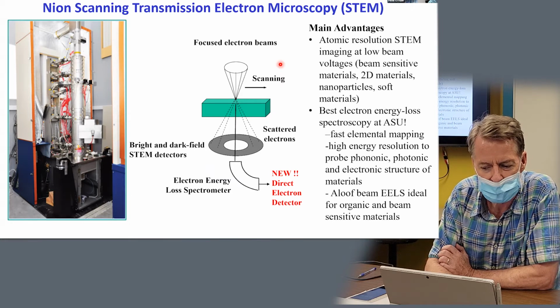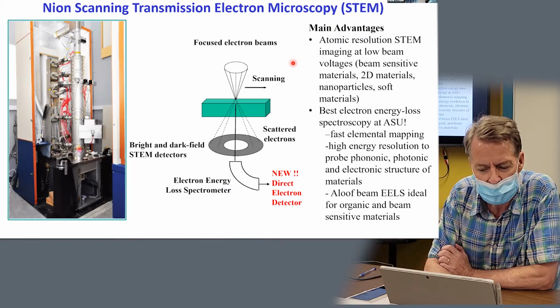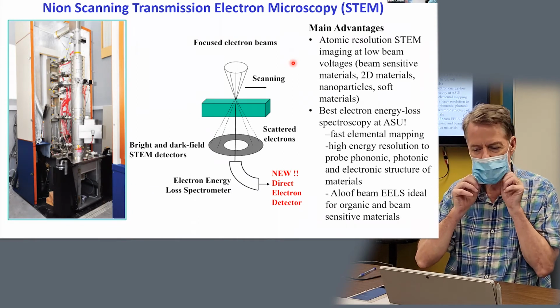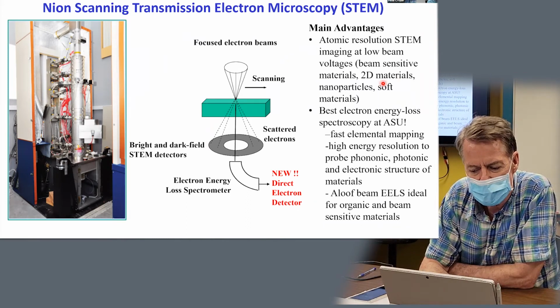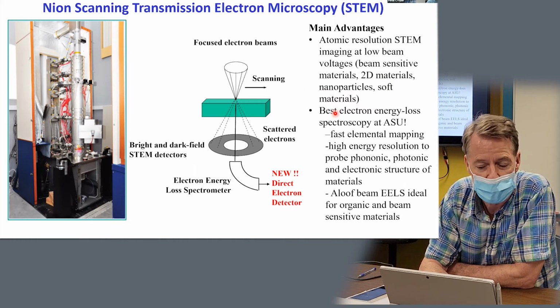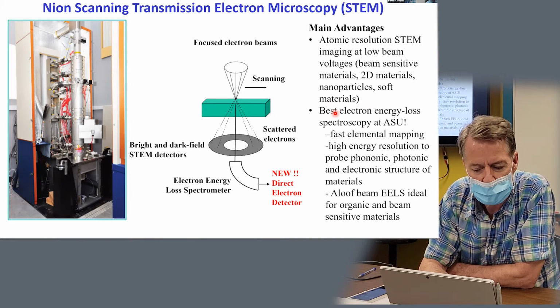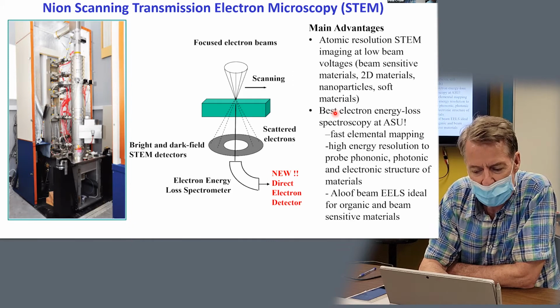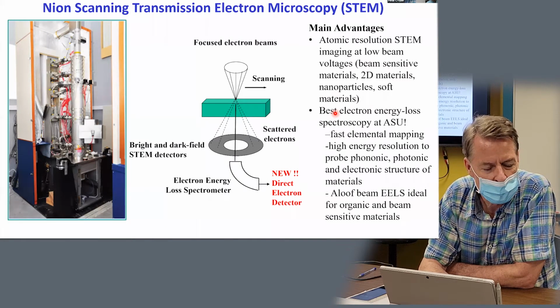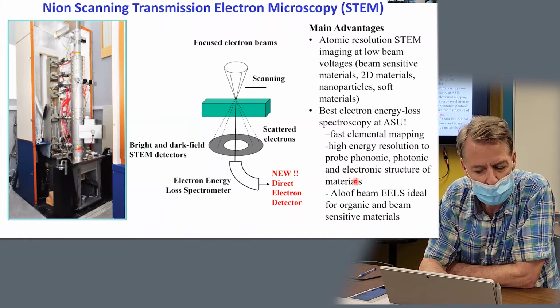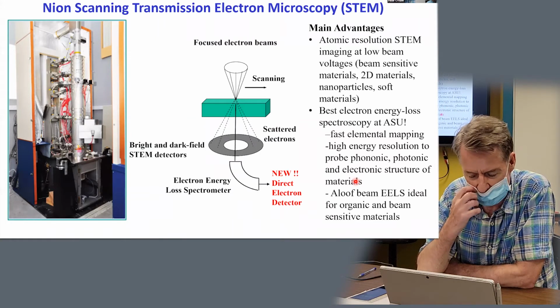The main advantage of this microscope is that it can perform STEM imaging at fairly low beam voltages. So that means it's very good for beam-sensitive materials, two-dimensional materials, nanoparticles, and soft materials. The other main feature about this microscope is that it has the best electron energy loss spectroscopy capability on campus. And especially with the new detector, it really allows us to do very fast elemental mapping. It allows us to probe electronic, phononic, and photonic modes. And using a technique called aloof beam spectroscopy, we're able to also probe organic and beam-sensitive materials.